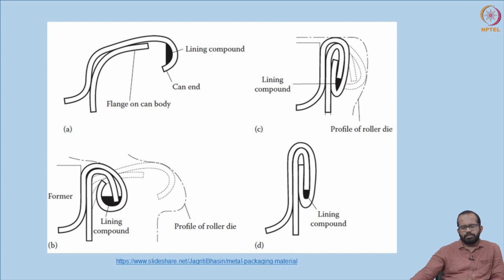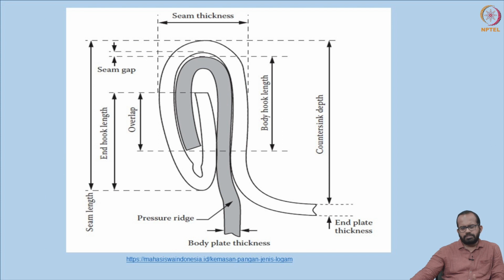If you take a cross section of a perfect can double seam, you can see different parameters such as seam thickness, and seam gap has to be measured. The overlap is one of the most important parameters in the case of a double seam. If you measure it, the overlap should be more than 40%. It should not be less than 40%. So for a perfect double seam, the overlap should be more than 40%. Other parameters are end hook length, the depth called countersink depth, and body hook length. These different parameters can be measured from the cross section of a double seam.